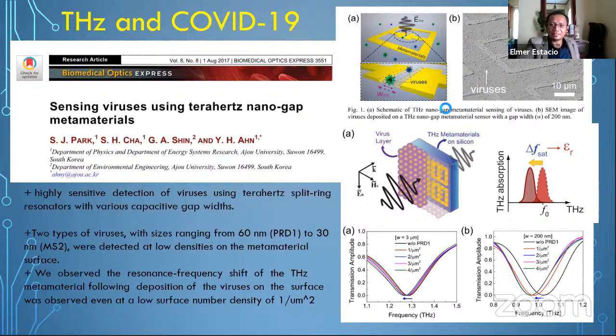So in their experiment, they are able to deposit a solution on this surface wherein they deposited metals having gaps within the range of a few nanometers, a few hundreds of nanometers, down to several microns. And they are able to see some changes in the transmitted terahertz light. And this change in the frequency peak of the transmitted terahertz light, if you put a virus compared with just the metamaterials with no virus present, shows a change in frequency that is sensitive down to 1 virus molecule per square micron. So this is the selling point of this work.